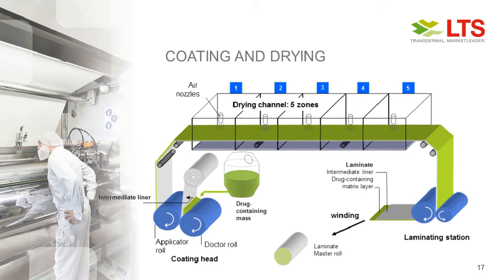So at the very end of the process, this dried laminate, in this case of liner and the drug-containing matrix, is wound up to create the master rolls. Depending on the coater, they can be from easily 20, 30 centimeters up to significantly above 1 meter.